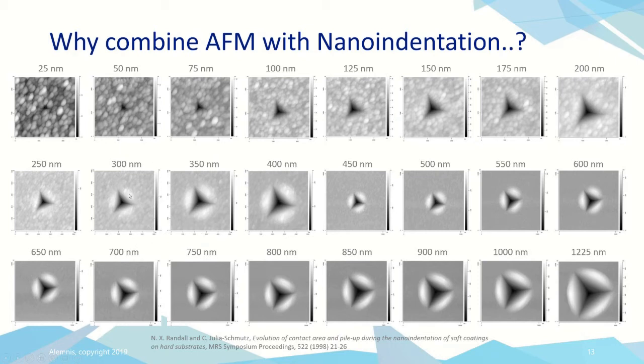And there we start to see pileup increasing proportionally as we go up in depth, okay? So obviously the depth of indentation is very important, especially in a coated system, to understand, are we really measuring the mechanical properties just of the coating or of the substrate, or is it a mix of the two? And AFM helps us to understand that.